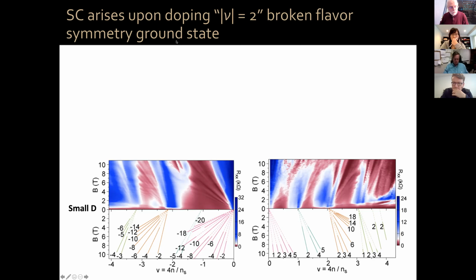Okay, remember that I told you that we had this cascade of phase transitions. At each integer, the system flavor polarizes. Well, at small displacement field, you can see if you measure the Shubnikov-de Haas oscillations as a function of perpendicular magnetic field, you can see these things pointing always outwards, away from charge neutrality. Okay, charge neutrality is in the middle. If you have holes, you point to the left. If you have electrons, you point to the right. Okay, that is telling you that at each integer, we have a reset where a new Fermi surface opens, which has a spontaneously flavor polarized system.